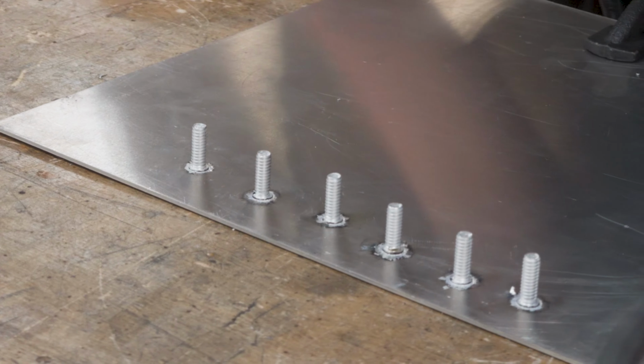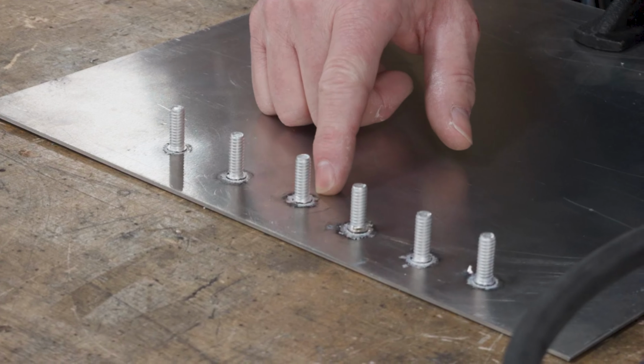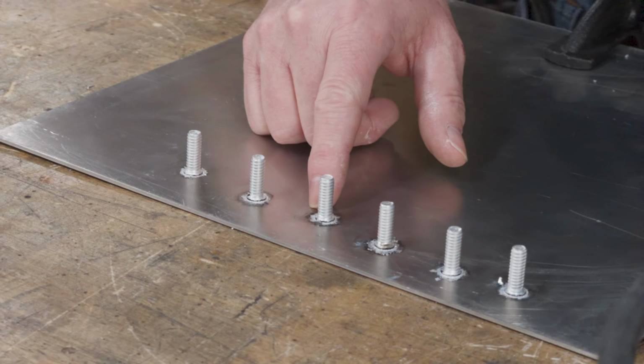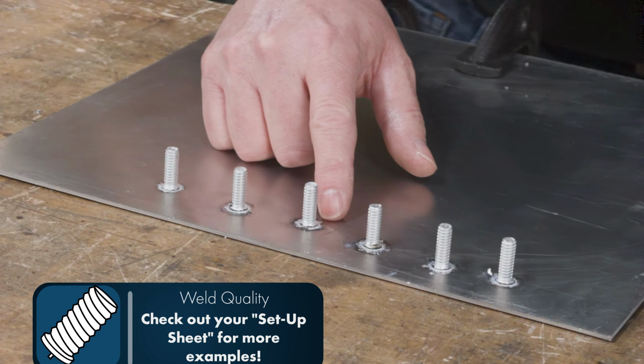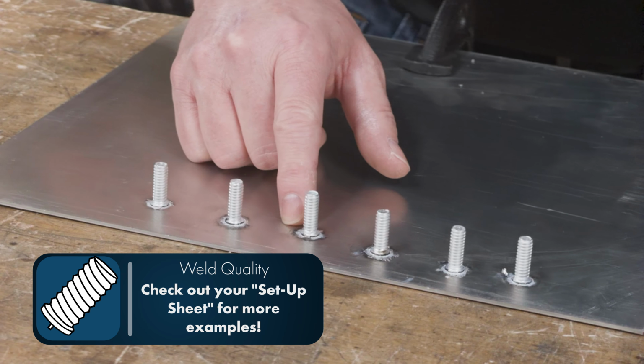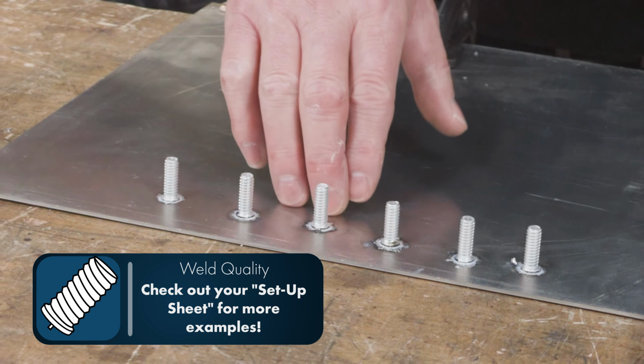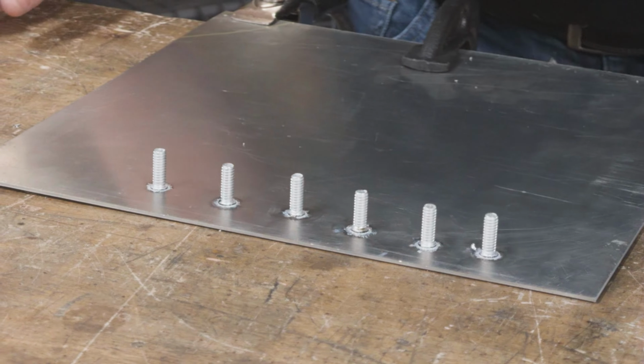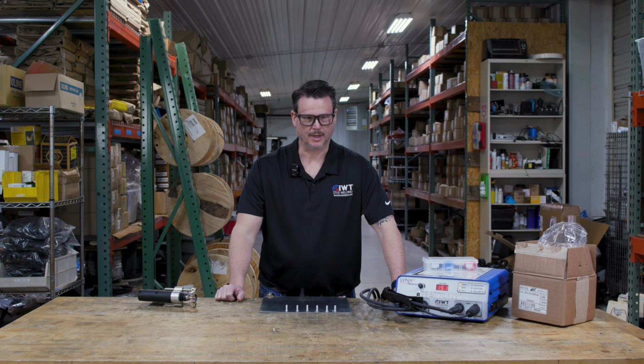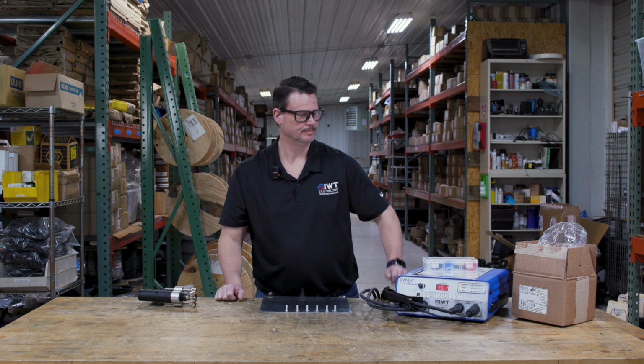What makes these good welds is 360-degree flash all the way around the head of the fastener, no pockets or voids in the weld, and that the head has almost been pushed into the aluminum. Now to show you what bad welds look like, we're going to make a cold weld by decreasing the voltage and then a hot weld by increasing the voltage.